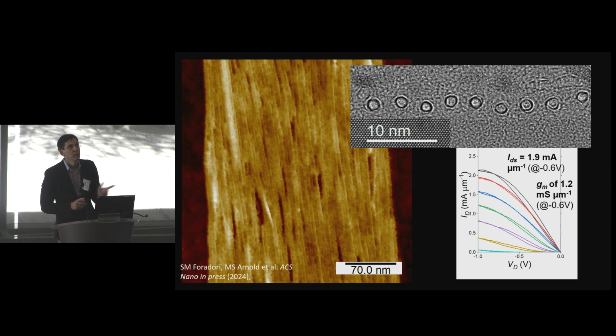Here, this cross-sectional TEM shows a tube spacing around 3.5 nanometers. The AFM on the left is like a top-down view. It's not perfect yet, but it's really close to what we'd want for a transistor. And we've made transistors, and they're pretty nice transistors. Really high current densities, but we have a lot more work to do. We can't yet achieve this uniformly on a 300 millimeter wafer scale, but we're getting closer and closer.